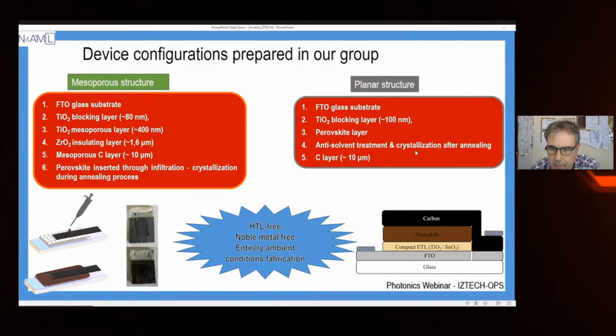The basic difference between the two technologies is that in that case here we bake the carbon at 500 degrees, but in this technology we can put the carbon on the top at a relatively lower temperature, around 100 degrees. So you can see that this technology can also be transferred to flexible substrates, which is very important also for organic electronics and generally for new applications of solar cells.